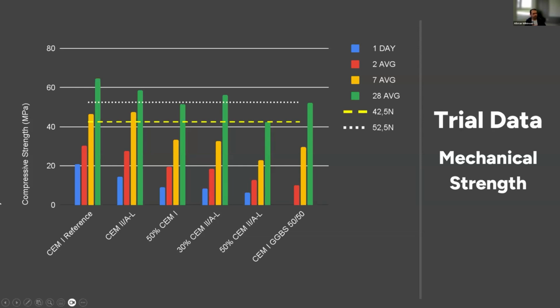So what we found was that with the 50% CEM1 replacement, we're able to hit in towards a 52.5 strength class. So falling within the boundaries of what most of the CEM2s on the market are. So getting decent early strength, but really starting to see that strength develop over the longer period of time.